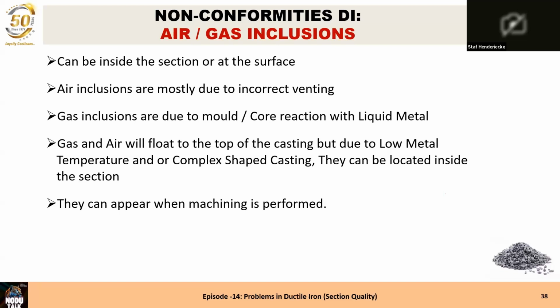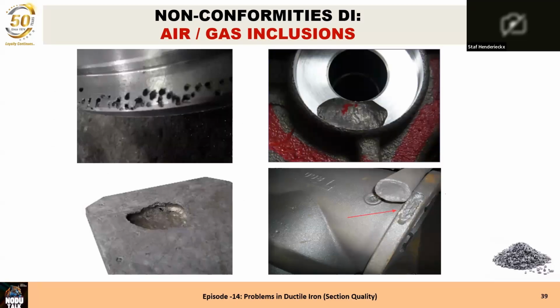Gas and air will always float up to the top of the casting, but if the metal temperature is low or the casting has a complex shape, it can be located all over inside the section. Most of the time they appear only when machining is performed, and then it's not making our customer happy. So you can see here, the first is air, a lot of air bubbles. The other one is a concentrated air, but mostly gas is also involved in that. The third one below had a very, very thin solidified covering section, but when you touch it with a hammer you can see it. And the third one is definitely lack of venting, so that the air is staying there.